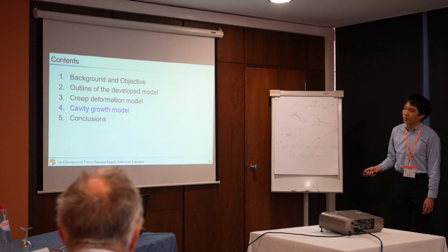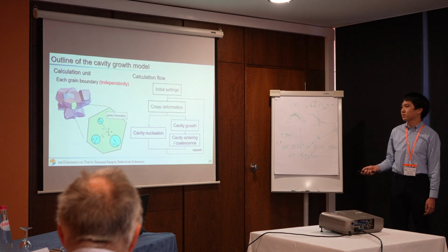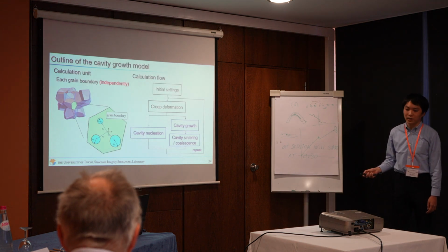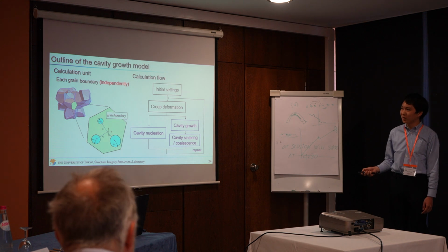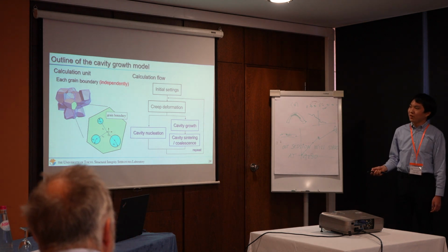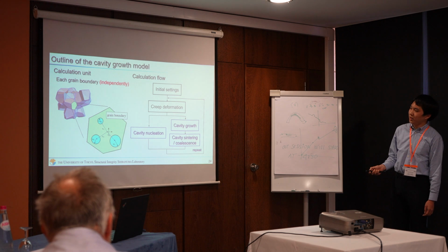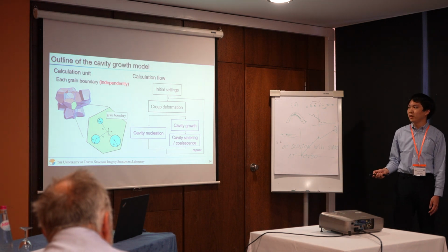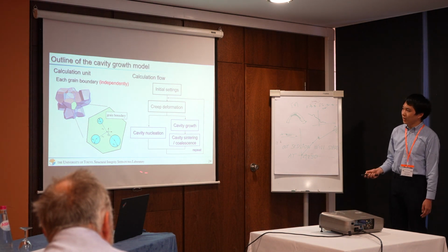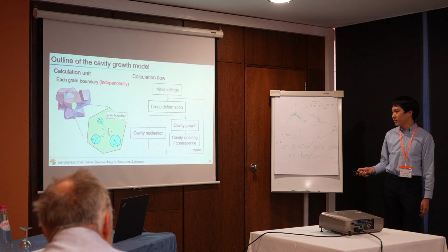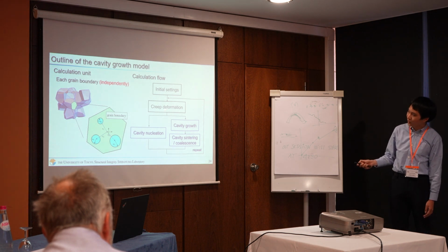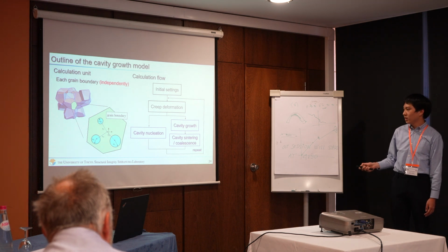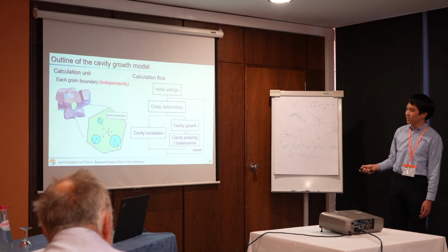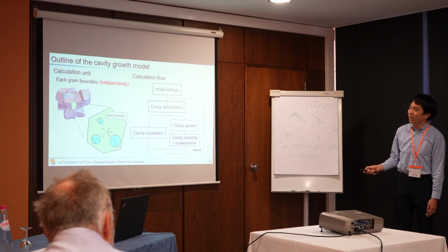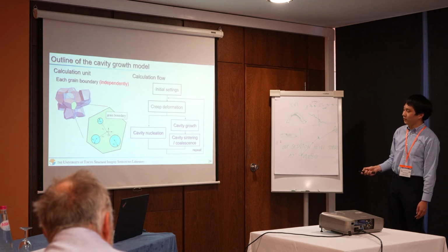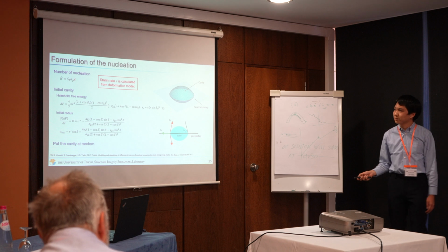And next, I talk about the cavity growth model. This is the outline of the cavity growth model. We calculate cavity growth and cavity nucleation at each grain boundary independently. And this is the calculation flow. After the creep deformation I explained before, cavity nucleation, cavity growth, and cavity sintering and coalescence are calculated and repeat this flow again and again.